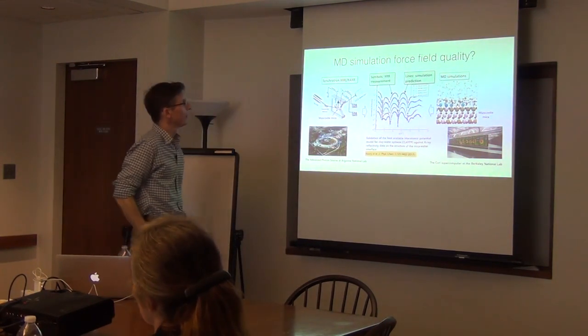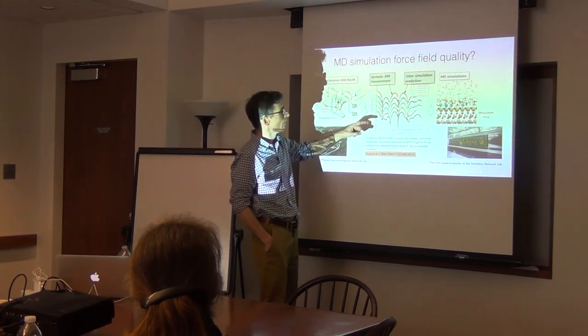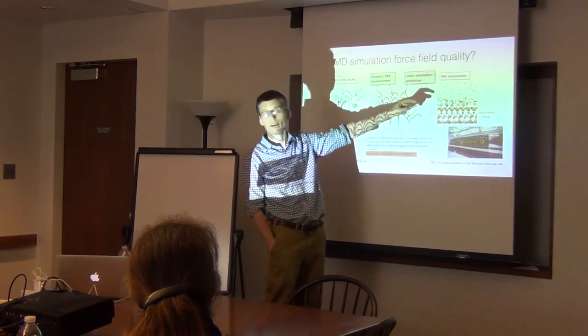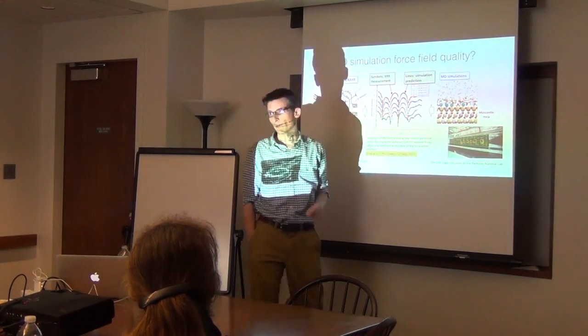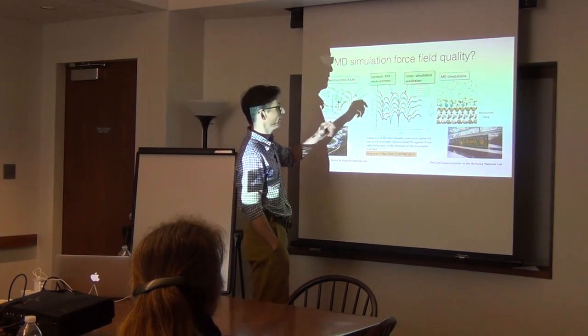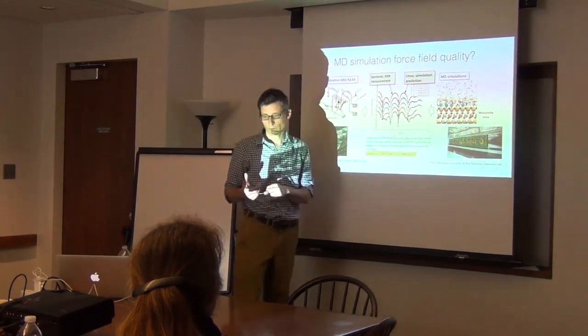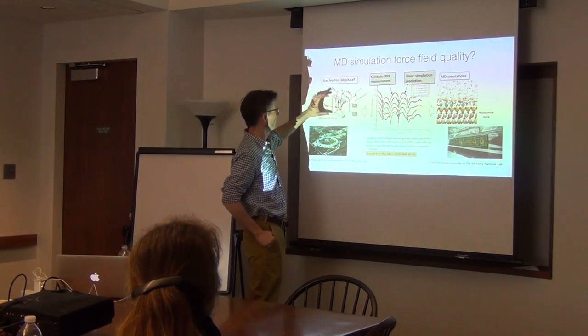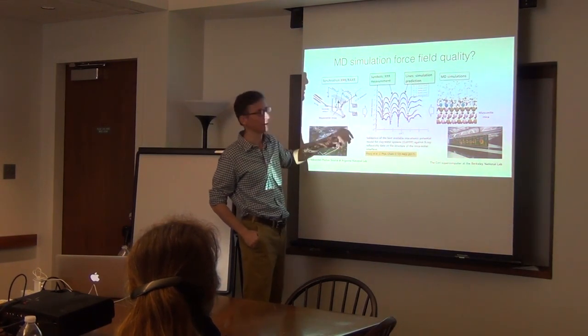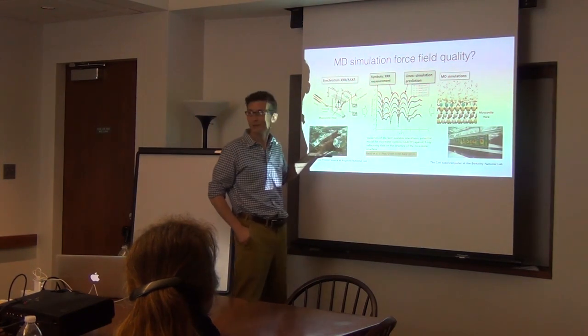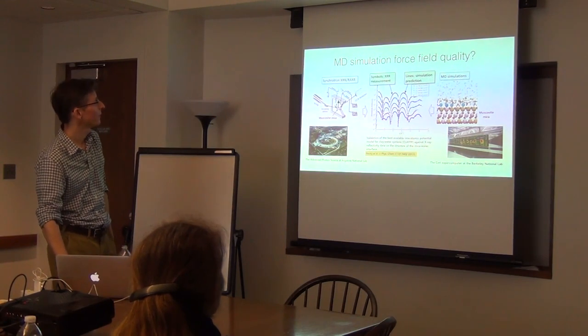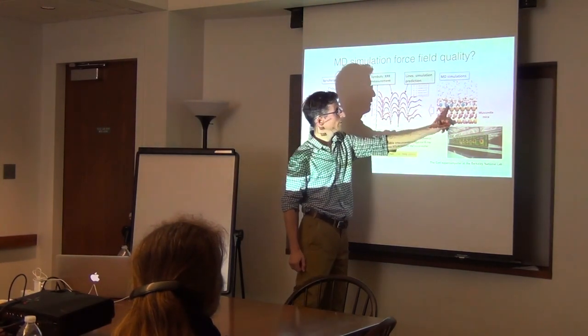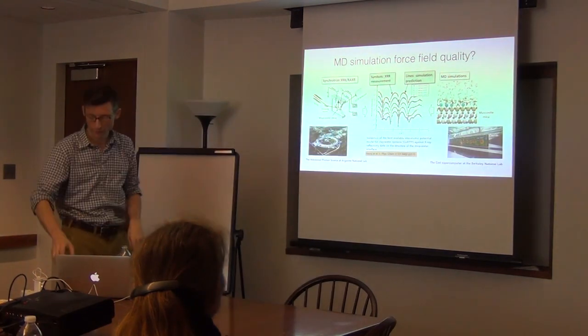The water model is SPC/E water, which has been around for about 30 years. For the clay, it's using ClayFF, which has been around for about 10 years. Nobody had actually tried this comparison previously. When we tested these force fields for other properties like transport properties of water and ions in clay interlayers, we also got good agreement. This is basically telling us that the best available models do a really good job of predicting what's going on on the basal surface of the clay, which is 99% of the surface.